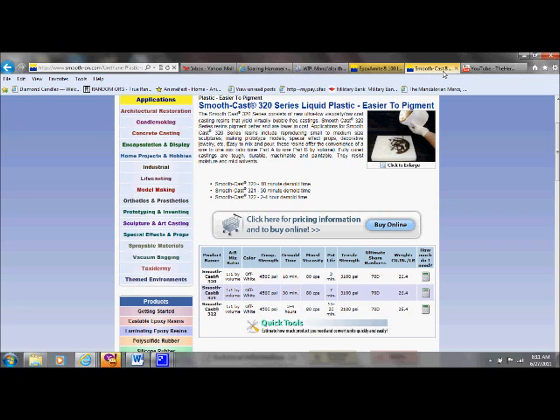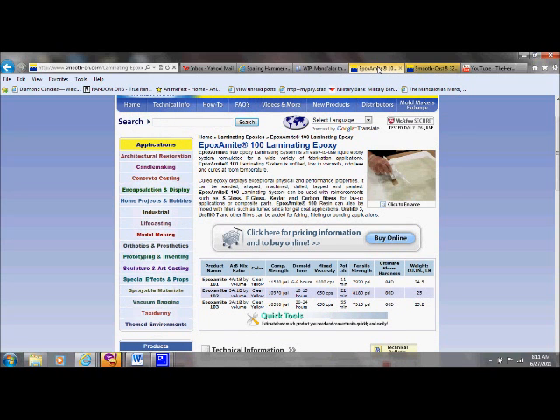It has a 7-minute pot life. That means what's in your cup is going to harden within about 7 minutes, give or take, depending on temperature, because they are both affected by temperature. The hotter it is, the faster it's going to flash. So you can brush on the Smoothcast 321 and you have 30 minutes for it to harden. Now, here's the big difference between the Epoxamite 101 and the Smoothcast 321. The Epoxamite 101 is 6 to 8 hours demold time, 11 minutes pot life. So you have 11 minutes before it will harden inside your cup, but you have to wait 6 to 8 hours for this to cure.